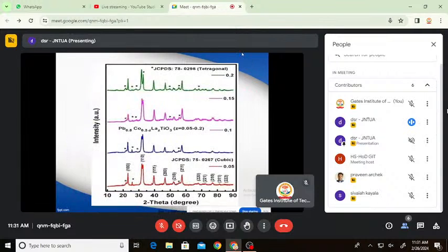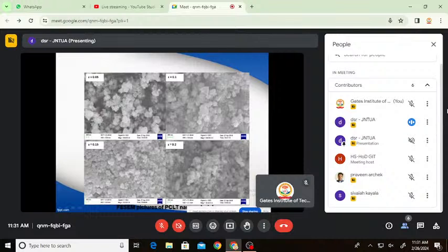So coming to FESEM analysis, these are the images of PCLT nanoparticles taken from SEM. Here also the lanthanum composition has been changed from 0.05 to 0.2. From the images, it is clear that the 0.05 and 0.1 samples exhibited an inhomogeneous distribution of stone-type grains. For y equal to 0.15 content, it exhibits a few square and stone-like grains having a homogeneous distribution.